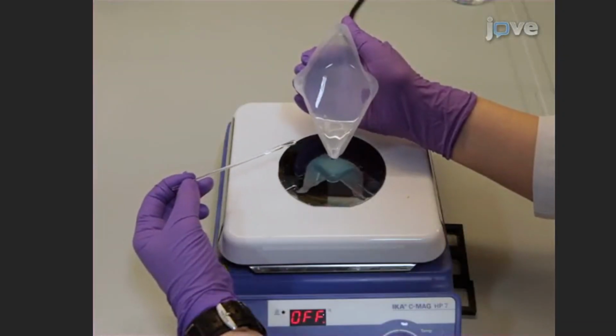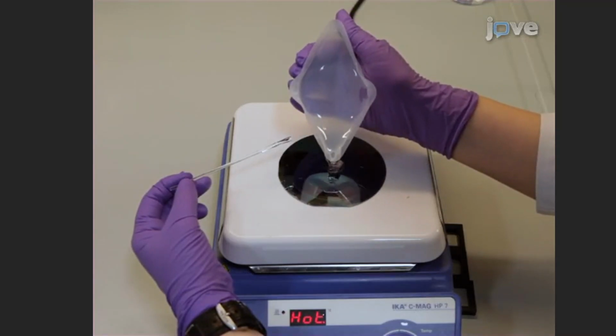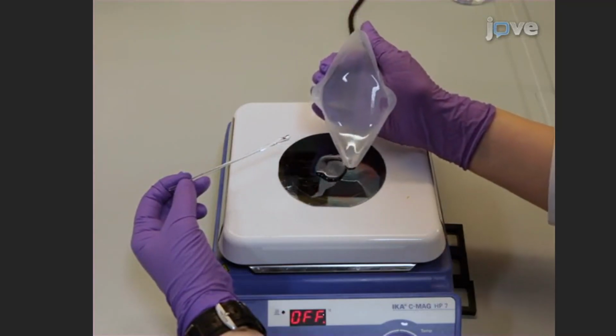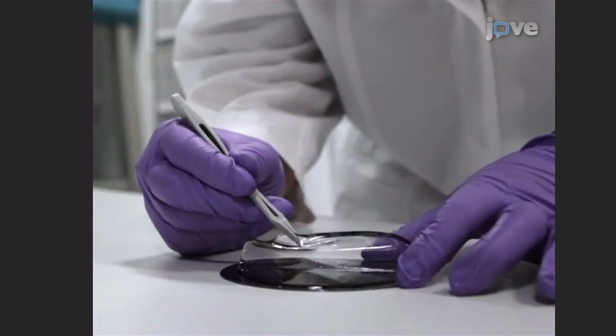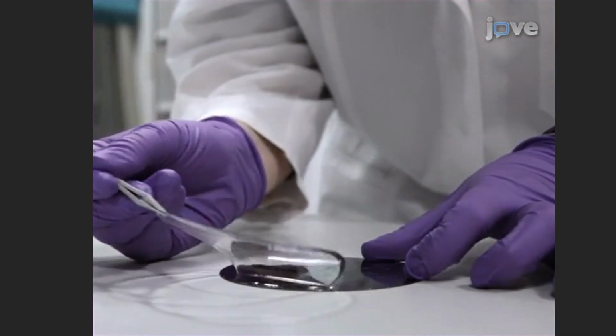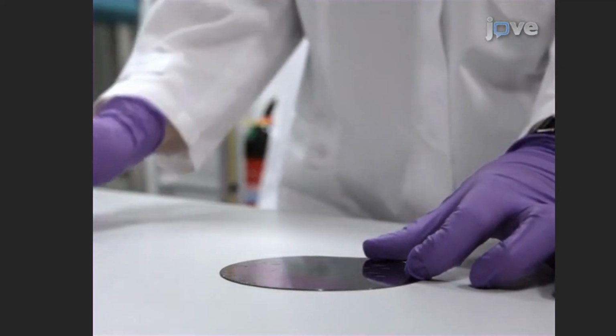Apply the remaining PDMS to the entire wafer in order to protect it during storage. Upon peeling this PDMS layer off the wafer, any particulate contaminants are removed from the surface in readiness for repeat PDMS molding.